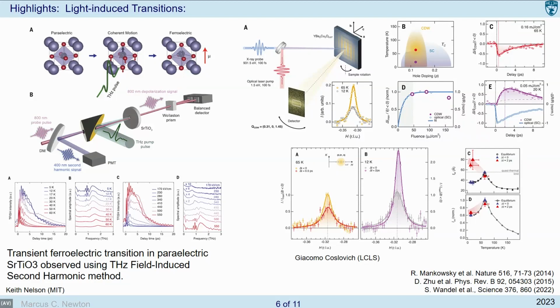So they have a paraelectric strontium titanate material. We're able to look at the ferroelectric transient state by pumping into this state with a visible laser. The main point here was that we're able to see a renormalization of the phonon modes to reveal this hidden phase effectively. And so you could imagine this being extended into the X-ray regime. This was an early important study, which was the impetus for further work looking at the properties using an X-ray source.